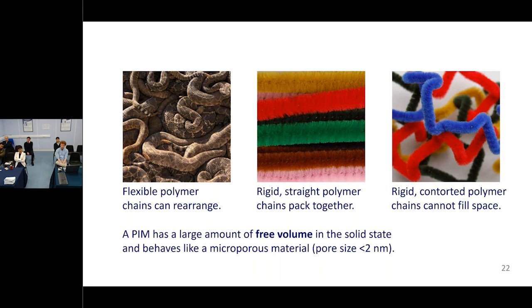The shape that it has is fixed at polymerization, and although it can wiggle a little bit and flex a little bit and bend a bit, it can't undergo those large-scale conformational changes that a normal polymer can. And so it traps a lot more of what we call free volume, a lot more space in the solid state than a normal polymer. And the consequence of that is it behaves like a microporous material, where we're talking about a material which behaves as though it has pores less than a couple of nanometers in dimension.